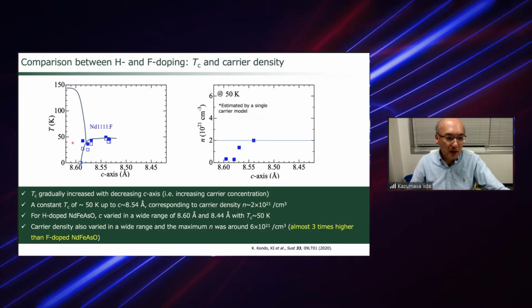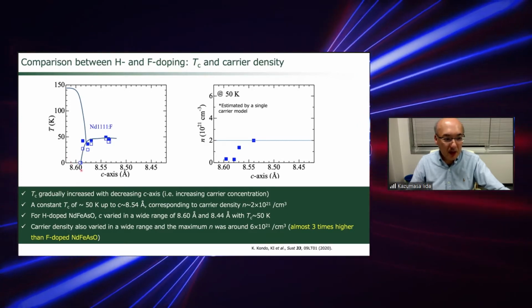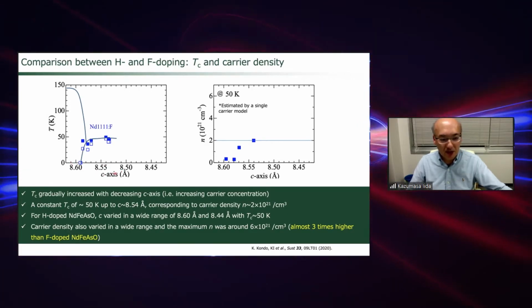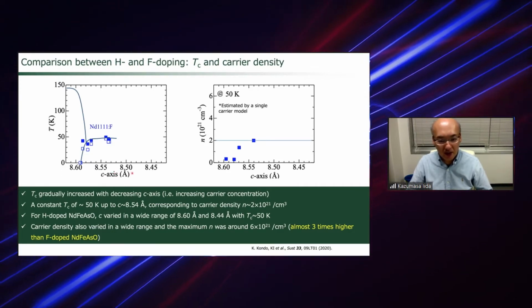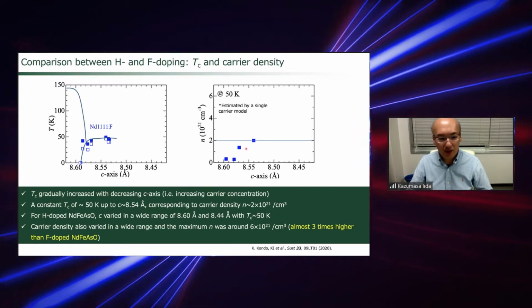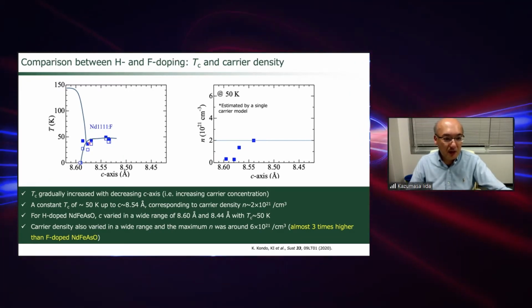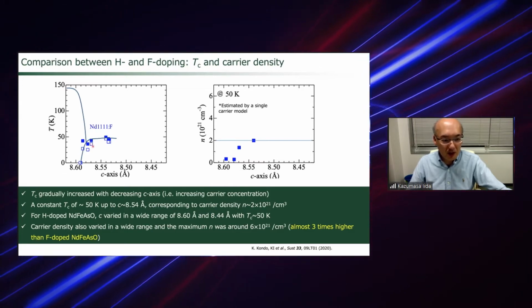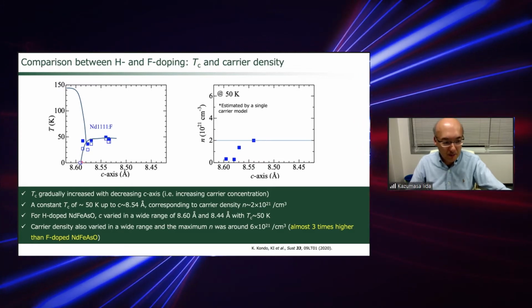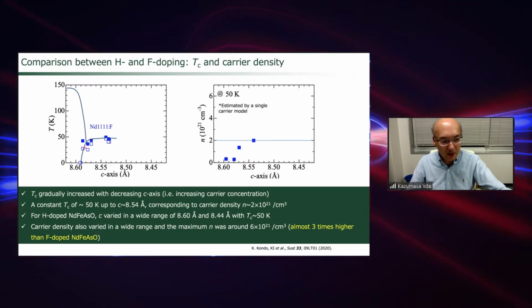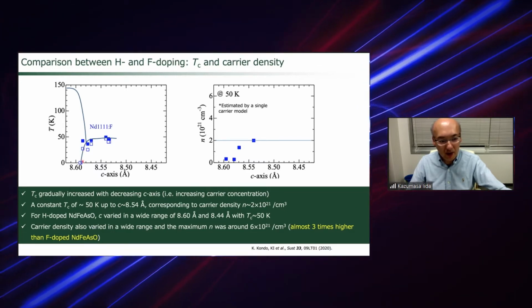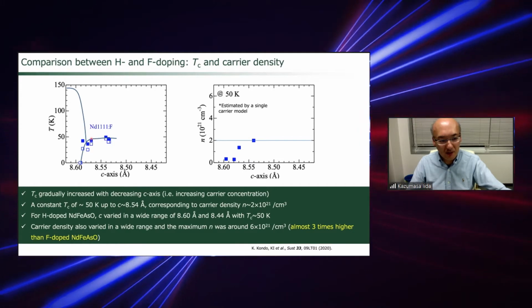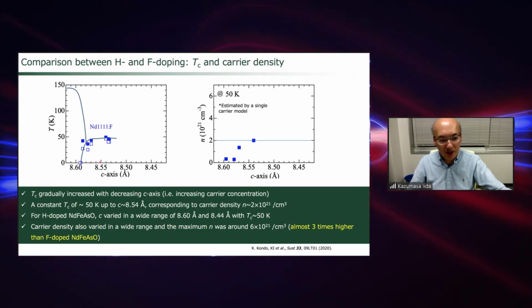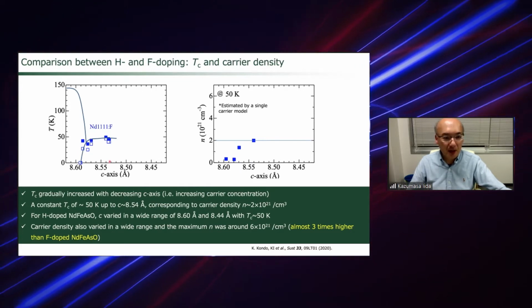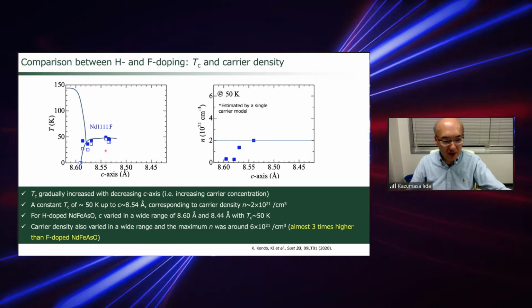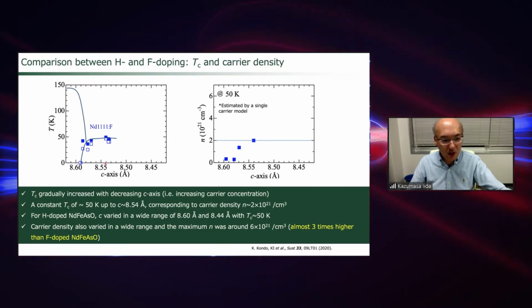Okay, now we plot the superconducting transition temperatures as a function of the C-axis length, because the C-axis length correlates with the carrier density, as shown on the right-hand side of the picture. These solid symbols represent the onset TC, and open symbols represent the zero resistance temperatures. When we dope the fluorine, only a small amount of fluorine induces superconductivity with a TC around 50 Kelvin, and at the same time the C-axis lattice parameter decreases, up to where the C-axis length reaches 8.54 angstrom.